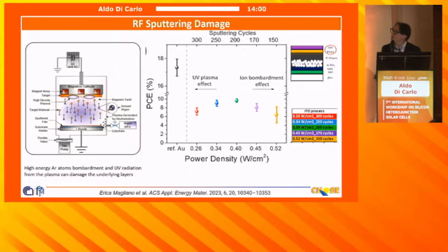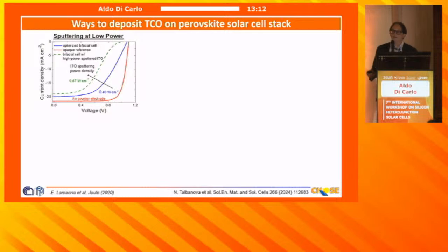There are several ways to do it, but where is the problem? When we use conventional RF or DC sputtering, we have this plot of efficiency as a function of power density. The reference cell has the evaporated metal contact. When you sputter ITO on top, at low power density we need a lot of cycles, so we have a UV plasma effect. At high power density we need fewer cycles to get the same thickness, but then we have a lot of ion bombardment effect. At the very end there is a maximum, but still we are quite below the efficiency of the evaporated one. To solve this problem, one can use, as I said, low power.